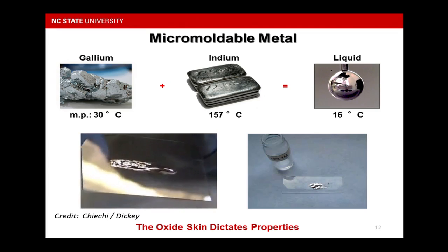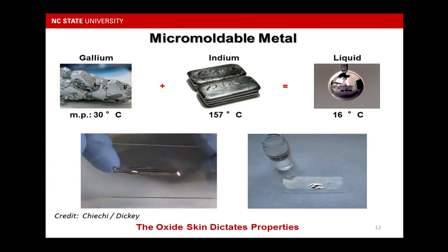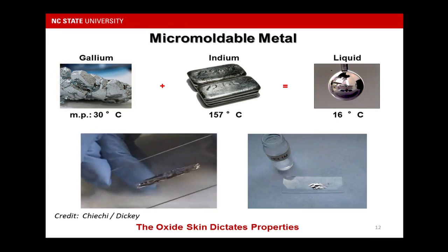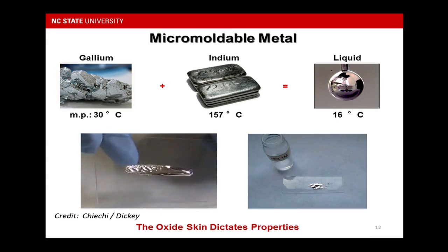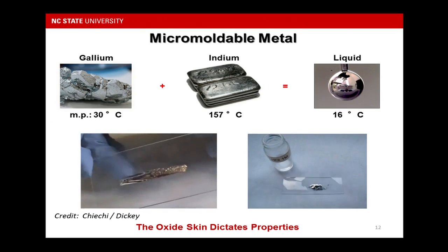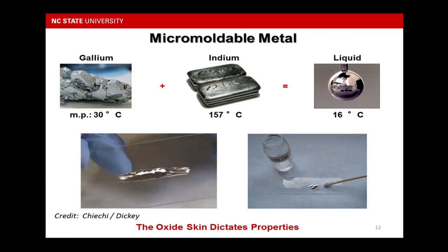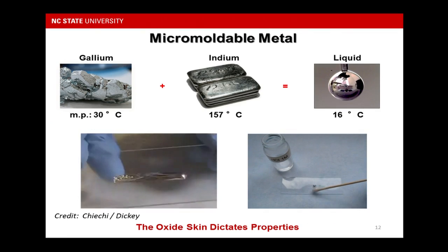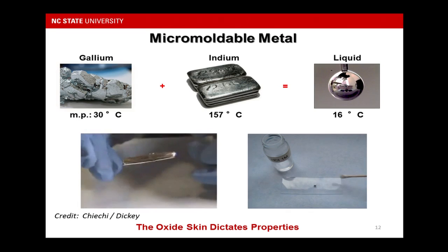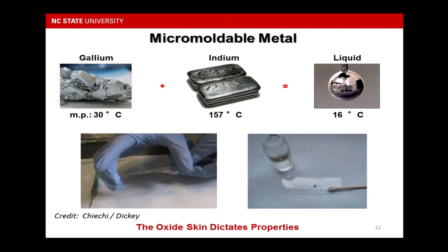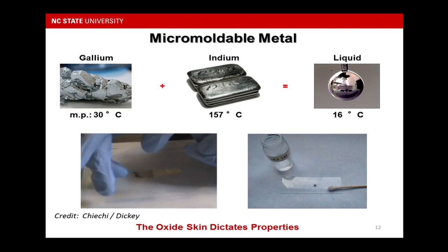The key point is that a few nanometers thick oxide skin forms instantaneously in the air on this liquid metal, which dictates properties such as the shape of the liquid metal. However, by adding acid, in this case one molar HCl, you can remove the skin on the liquid metal, so finally it will behave like mercury. But compared with mercury, this material is non-toxic, or as we will see, low toxic.